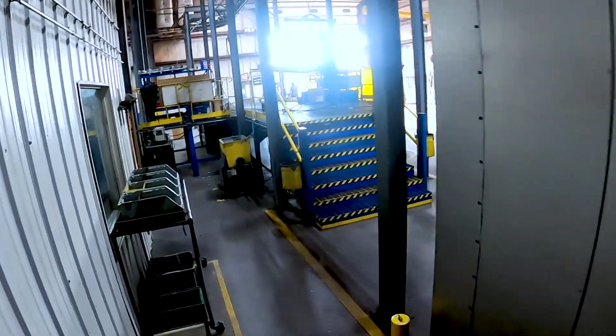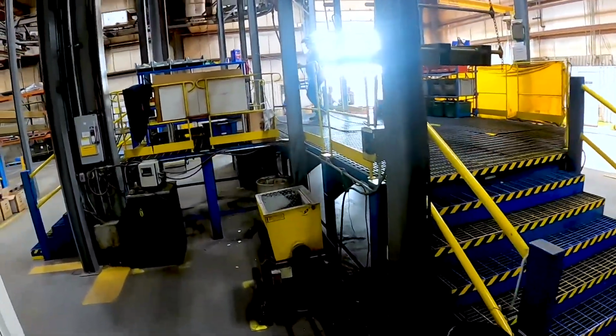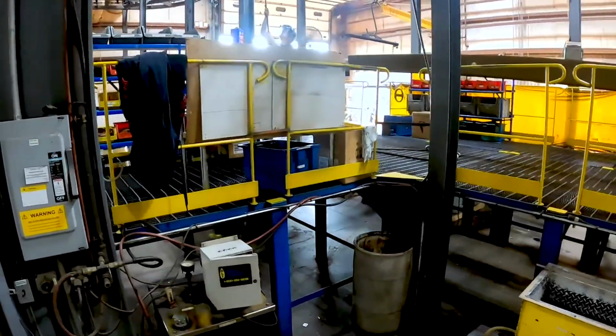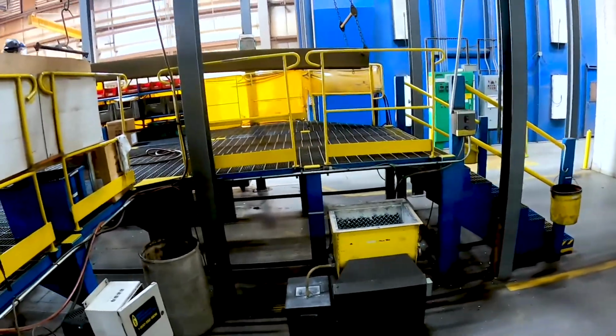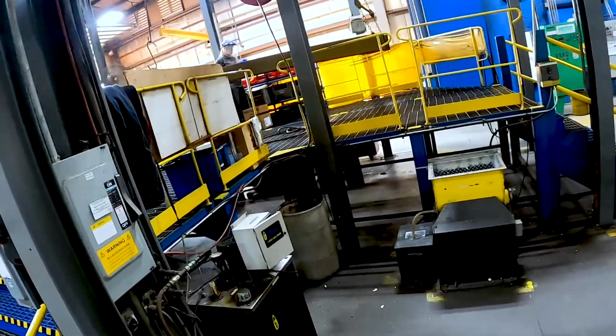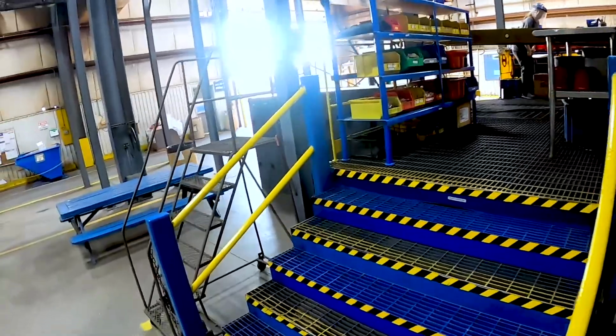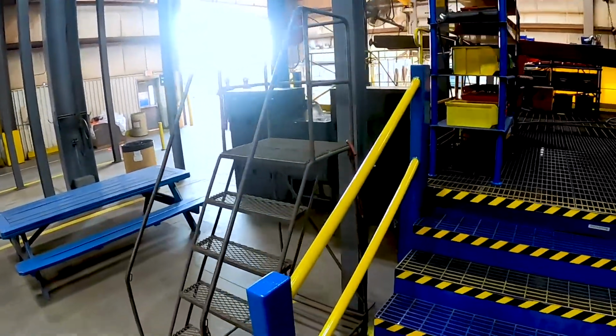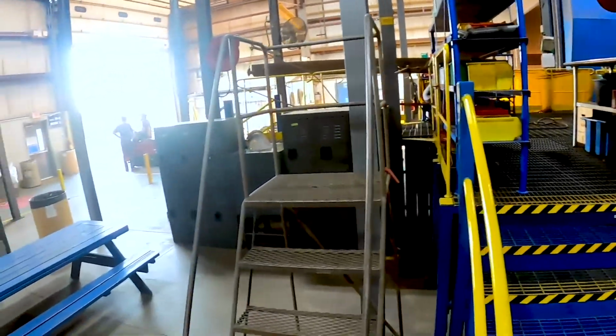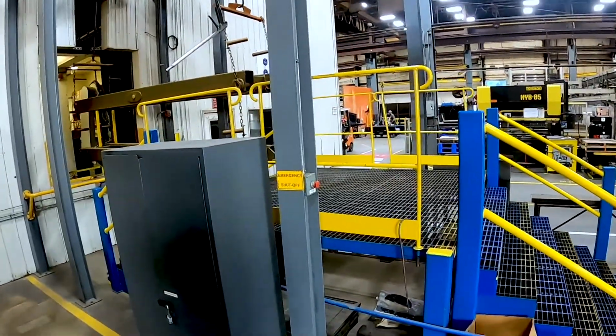our plugger will then go through, blow off the whole carrier, make sure there's no water, no shot, no debris. She'll also be checking the coating color to make sure that it doesn't look like it's flash rusted, that the coating's not too heavy like a white haze. And then she'll plug the bores or mask off threads or put plugs over the threads or anything the customers ask us to keep paint off of. Once she's done with it, but she has to keep things moving as much as she can, she'll send it around the bend over to the paint room.